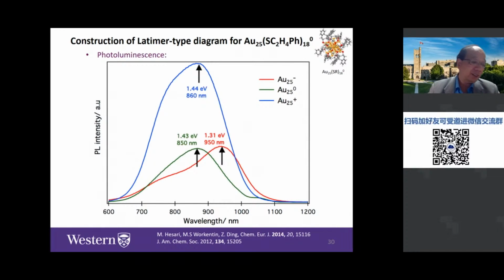Then we measure the photoluminescence, get these peak wavelengths and convert them to electron volts. In this way, we can link different gold clusters and their excited states. For example, gold 25 negative charged is the red one, with a peak wavelength of 950 nanometers. And gold 25 zero is the green one, with an 850 nanometer peak wavelength, but the emission is kind of moderate. But if we use gold 25 plus, you can see we have 860 nanometers, this is the blue one, but much higher, more than twice higher. So in this way, we can distinguish these three species via the light intensity and also the wavelength.